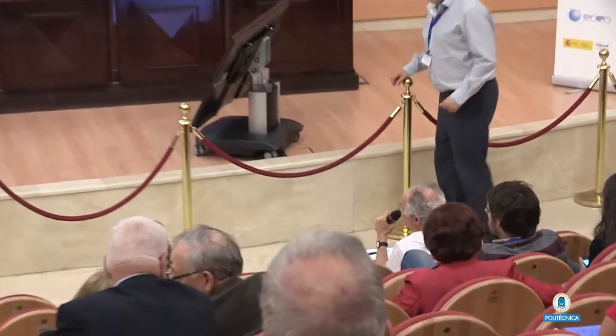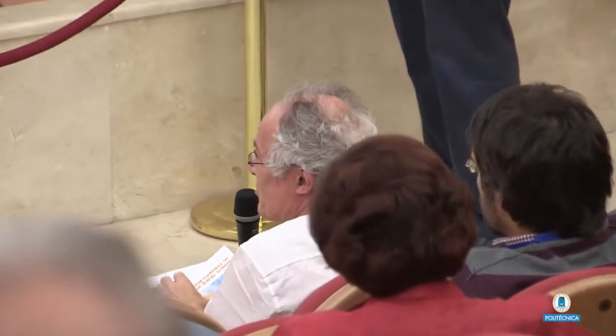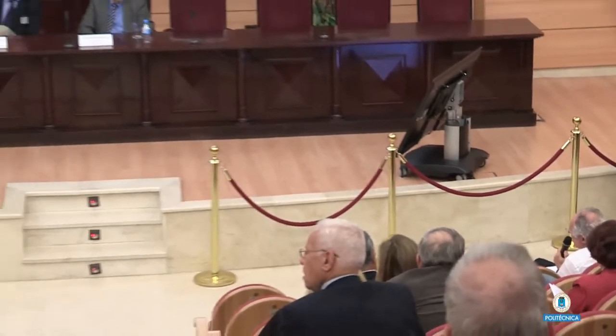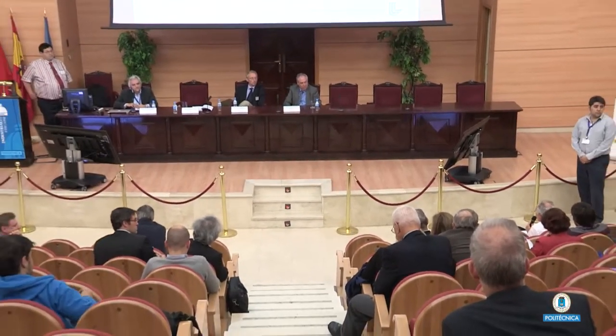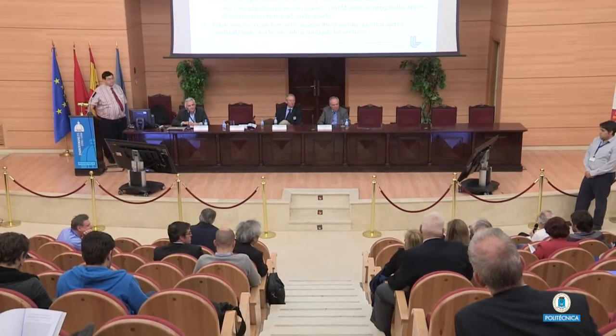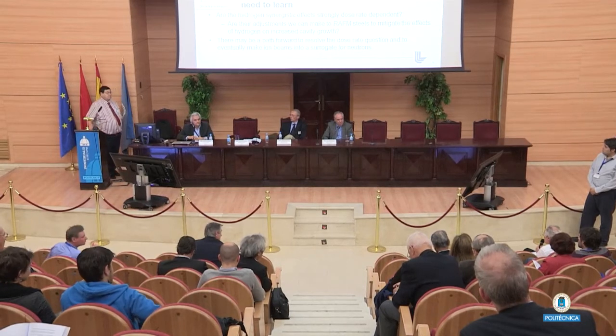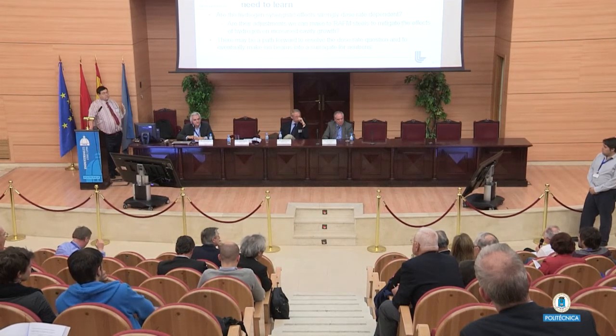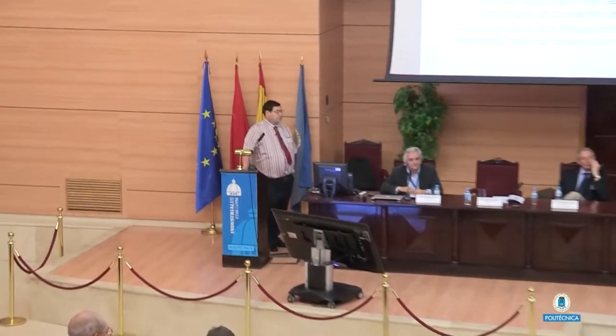Thank you, Mike, for a very clear insight in the comparison between ion and neutron damage in materials. Of course, all of us would like to have a possible extrapolation route and use ion beams extensively. One might be tempted, in order to accelerate the dose, to increase the intensity of the ion beam, and one might have thermal effects due to these beams if we go too high in intensity. Did you evaluate the effect of this thermal effect? Because you could also get an extra thermal annealing contribution. Is this an important factor or not?